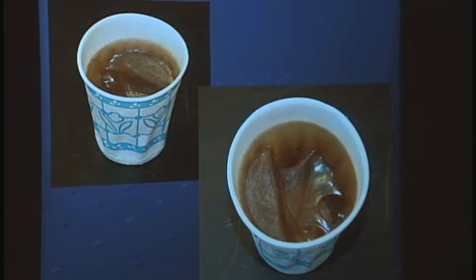Now, one of the seductions of hide glue, hot hide glue, is that we think it becomes solid at a fairly early stage of the drying solution, but in fact, it's just gelation from cooling. And even though it doesn't flow and has a very high rubbery character to it, well, you know, it sort of feels like a solid or will be a solid, but in fact, it will not. It will form a webbed matrix, which is a real problem. It's a little hard to see that, but there is a fair bit of gap right here.